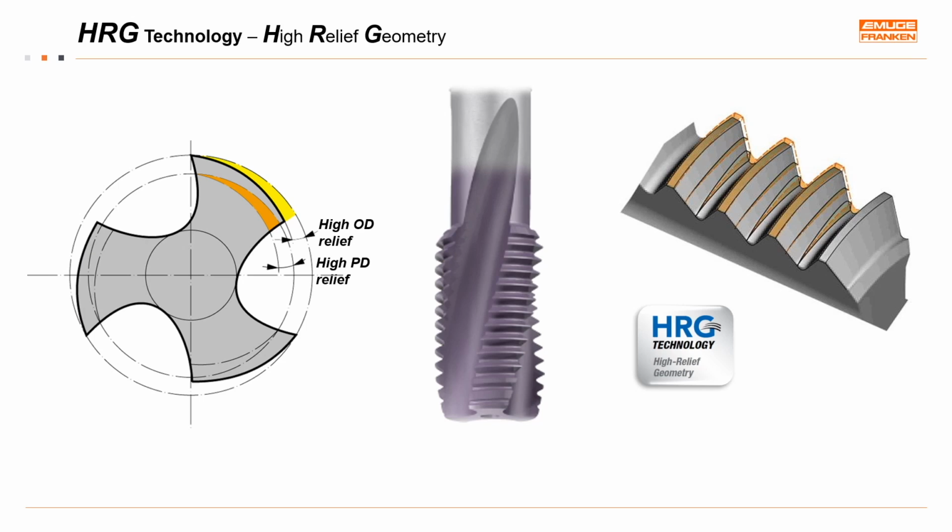HRG technology incorporates advanced high-relief geometry which increases space between the friction surfaces for enhanced lubrication and reduced torque load in both forward and reverse direction. HRG counteracts the high compressive forces produced by the extreme elastic memory of titanium.